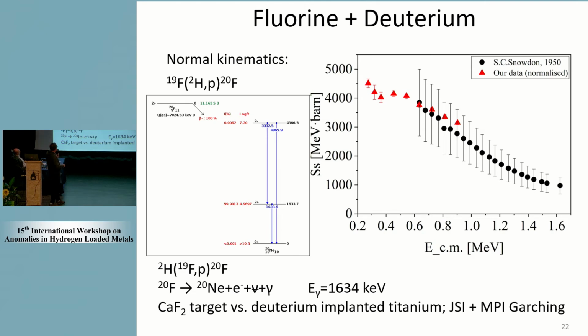This reaction produces fluorine-20, which is radioactive. Then this fluorine-20 decays and emits, in almost all the decays, this gamma ray here, 1634 keV. And that's the characteristic gamma ray to determine the cross-section. So we measure this characteristic gamma ray, change the beam energy, and at each energy we count the number, and we can determine the cross-section. So these red points are our results.